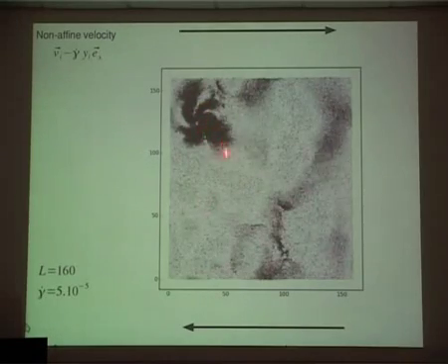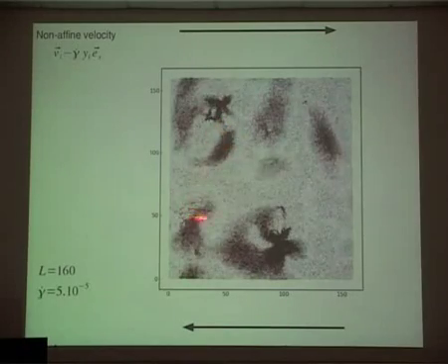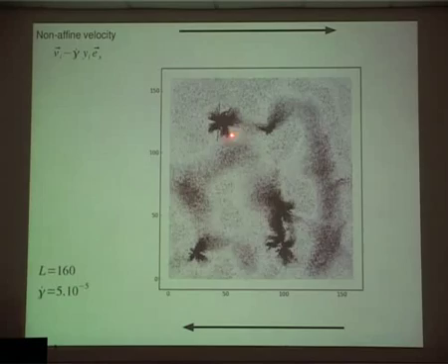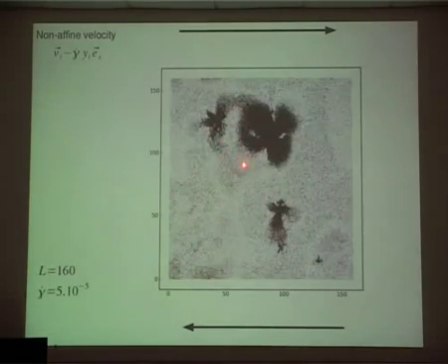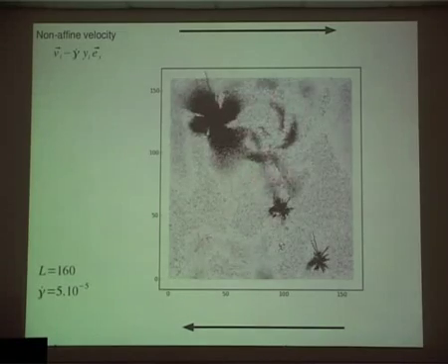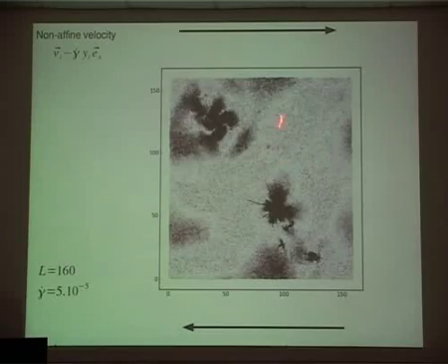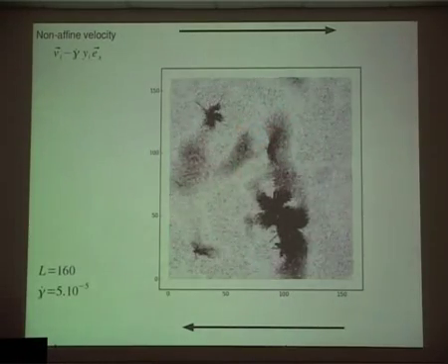And you see they come in very many types. Some rotate a little bit. The point here is that when you have this shear transformation, you see that the shear transformation emits information, which then propagates away. What you see here, now look, you see these waves which are propagating. In fact, they are waves. They are, in fact, shear waves.